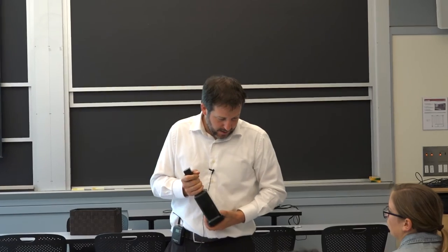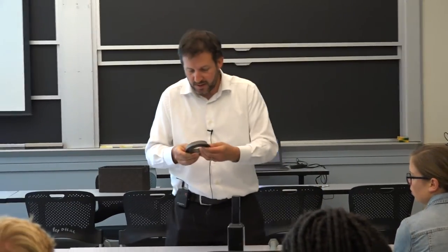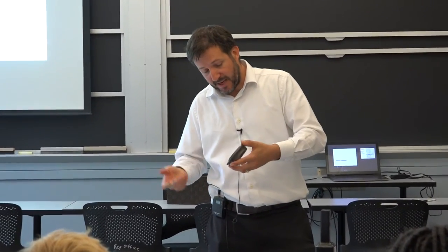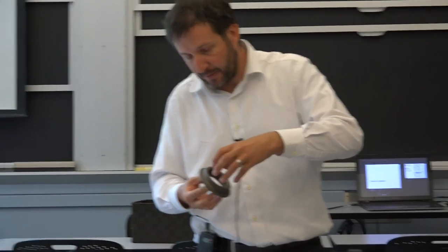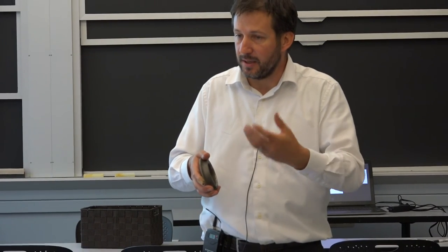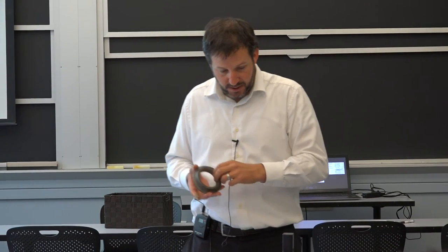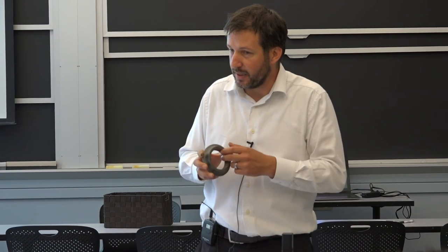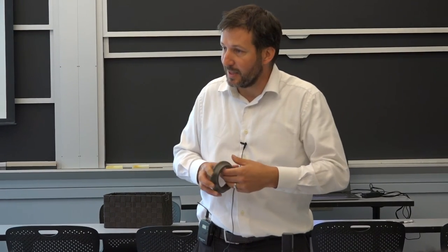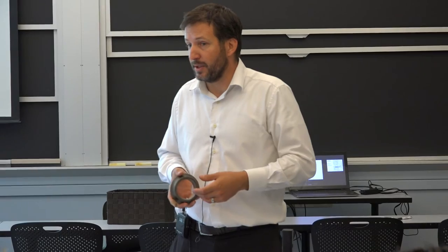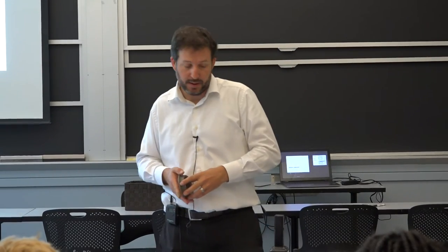So it's the same story with this one. This is a forging because it's to make a connection between a gasoline or other liquid tank and the pipe that comes out of it. If you cast this, you won't get the ductility and strength to allow it to bend instead of breaking in the event that it had to. And the reason it's threaded is you're not as dependent on the welder on site to put that on correctly. So it's mechanically interlocked, and the only thing that's going to happen, it's going to leak a little bit. And you'll know about it, but it's not going to completely separate, spray out, and burst.